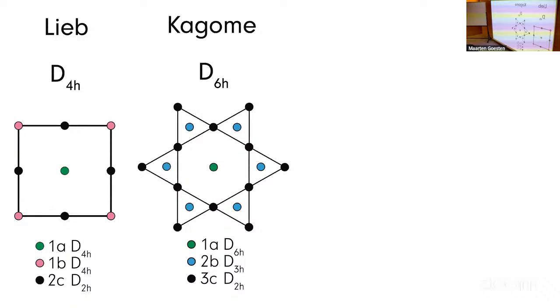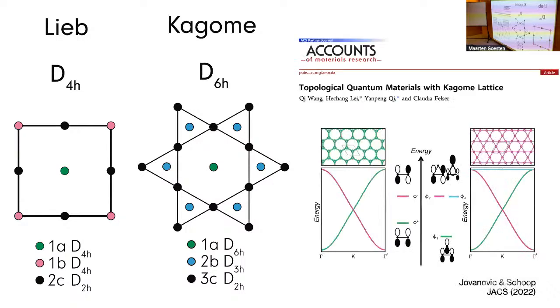control these things. And this is the Kagome lattice, which is receiving even more attention at the moment. A few weeks ago, I was actually at a Kagome meeting. And the Kagome lattice, what it gives you is fully prescribed by symmetry. It gives you a crossing, just like graphene, a symmetry-protected crossing, protected by a six-fold axis, but it also gives you this flat band. This is sometimes called the topological flat band, which sounds fancy, but the flat dispersion here is chemically very easily understood.